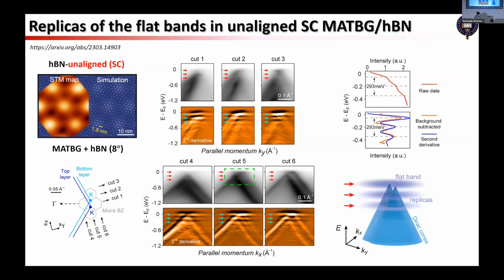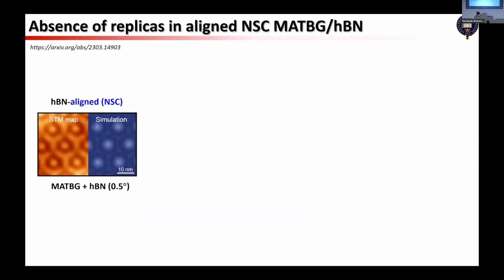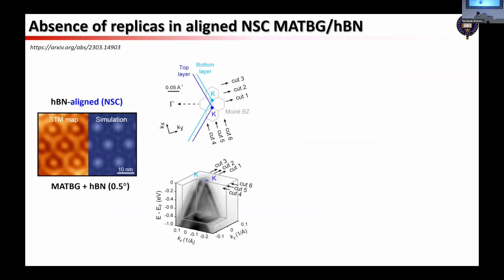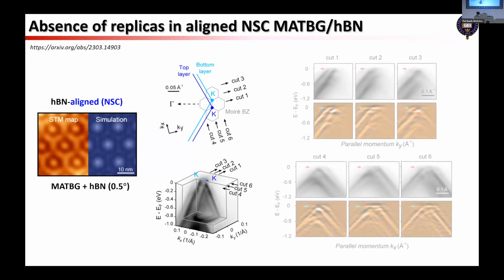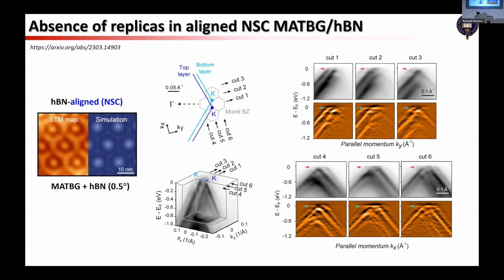So if we go to the HBN aligned sample, on the other hand, we were still able to see the bare bands, several of them. And if we do the same thing, cutting through a different angle at a different location, you can see that the dispersion now looks quite different.